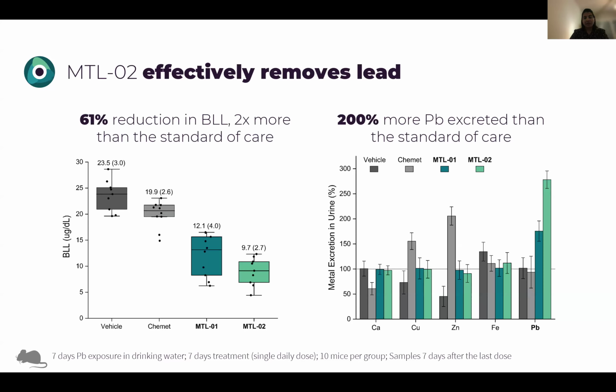And most importantly, in my opinion, is the graph on the right side, when we look at the urine. So we collected urine on specific days from each and every mouse and measured not only lead in the urine, but we also measured, from left to right, calcium, copper, zinc, and iron. And in all of those cases, we reached 2 important conclusions. First, our 2 peptides do not deplete the essential metals. There's no excretion of the essential metals. And this is something that unfortunately we cannot say about the DMSA that is depleting copper and zinc. And second, our peptides manage to increase lead excretion significantly more, about 200% more compared to the standard of care.